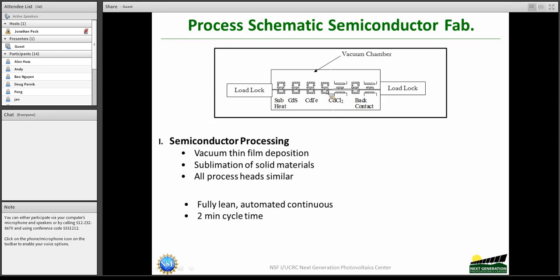And there are steps involved in subliming and removing the cadmium chloride. This is not left as a film. This is just a flux to aid in reducing the defects in the process. And then we developed this quite extensively, where you can introduce very small amounts of copper, typically 1 to 2 monolayers of copper, into the device to dope the back, and then the material comes out.